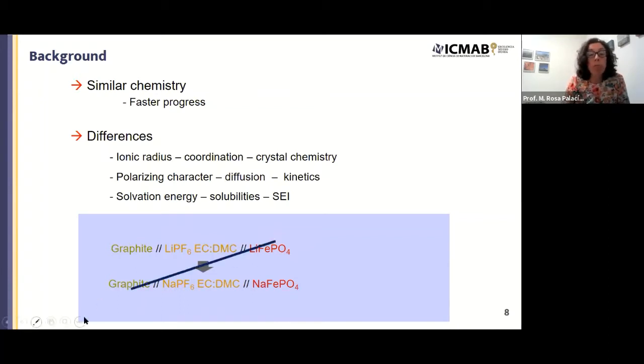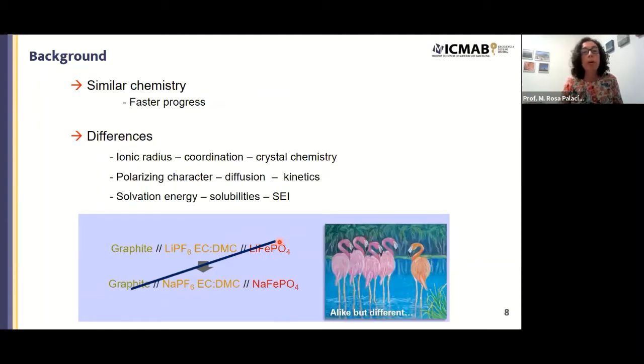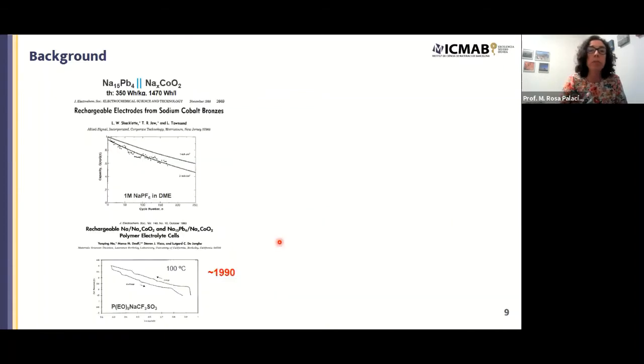First of all, graphite does not intercalate any sodium. So the only carbonaceous anode that one can use is hard carbon, which is a disordered carbon. And then when one synthesizes sodium iron phosphate, the crystal structure is different from this one, and there are no pathways for the diffusion of sodium ion. So really, if you want to prepare the same crystal structure, it is much more cumbersome. You need to prepare the lithium derivative, extract lithium, so it's not really that easy. So we need to bear in mind that both technologies would be alike, but there will be significant differences.